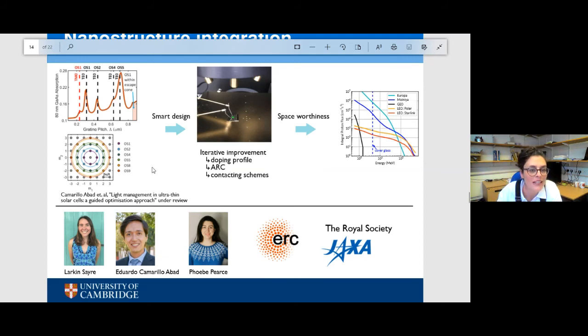So one is towards the more fundamental and looking at smart design. So here you see a little snippet of some work that my student Eduardo is looking at. So can we design our grating to be a much better match to our cell and so give much better absorption enhancement? So this work, what you see here is absorption in the 80 nanometer gallium arsenide absorber region. You can see the solid line being rigorous coupled wave analysis simulation just for a single wavelength. And the question is, can we change our grating pitch in order to give a better match to the optical modes that are available with the waveguide that we've created there?